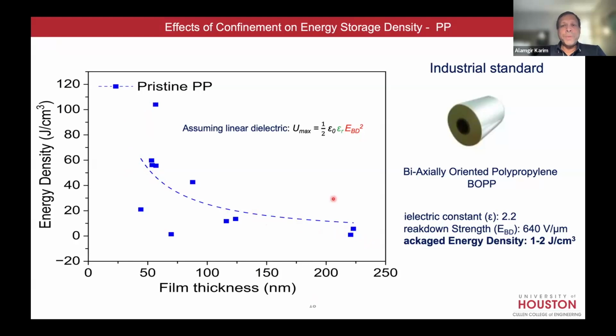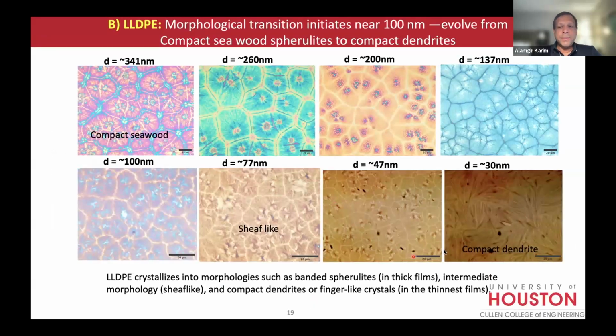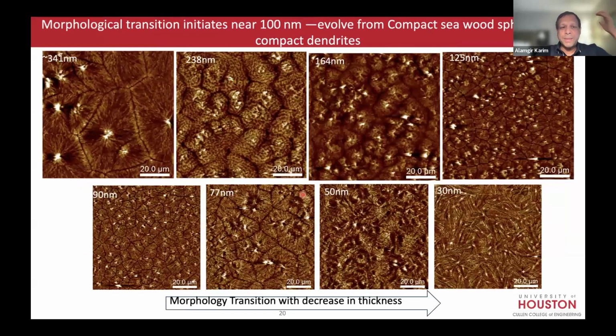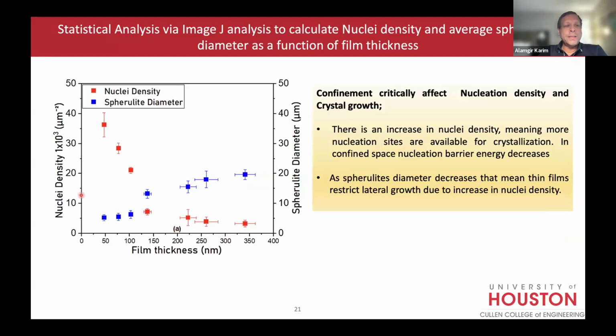So this is polypropylene. I will, in the interest of time, quickly move on to polyethylene. Just showing you LLDPE. Okay, these are the optical pictures showing you how the morphology changes. It's very cool, kind of pretty. You can then look at AFM, the same thing. You can see them more topographically, or you can get the phase contrast, mechanical property. If you look at the nucleation density versus film thickness, the nucleation density is the red. So thin films have high nucleation density, and then it rapidly drops off.